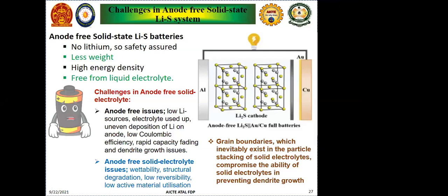So when we go to the lithium anode-free solid electrolyte, as we know with the solid electrolyte, there will be a wettability issue, like electrode and electrolyte interaction will be reduced, and their reversibility also will be an issue, as well as active material utilization will be reduced. When it is a liquid electrolyte, it interacts well with the electrode material, but in a solid electrolyte the movement will be less, and the electrolyte material cannot interact properly. So these are the major issues when we go for anode-free solid electrolyte batteries.